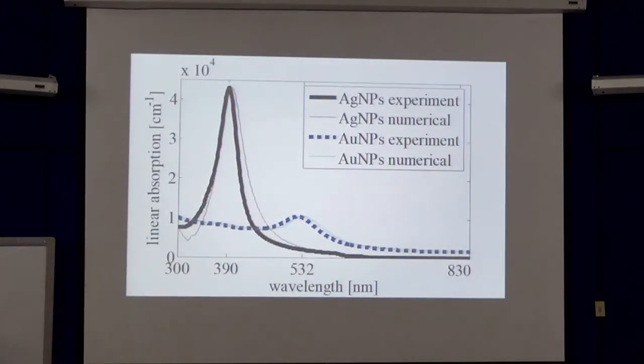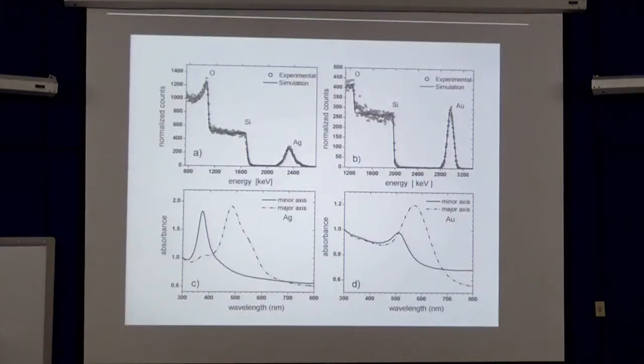You can use, for instance, here, it corresponds to silver, and it corresponds to gold. So if you use a wavelength, for instance here, a wavelength like here, you obtain a sign for the silver and a different sign for the gold in the same system. Or eventually you also can modulate the shape of the nanoparticles.